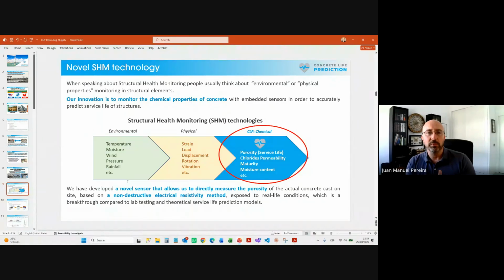What we correlate to with this non-destructive electrical resistivity method is the porosity of the concrete, okay? Porosity has an impact on everything because it shows you how the concrete is evolving. So it relates to strength, chloride permeability, carbonation, and also the maturity of concrete. It can also be related to damages that happen later, for instance alkali silica reactivity, which starts with micro cracking the concrete from the inside, and delayed ettringite formation, DEF. Any of these expansive damages increase the porosity because they form micro cracks. So we can detect both how the concrete improves over time and if these things happen, okay? And like I said, it's a non-destructive test, so we can measure this continuously. That's why it's a monitoring system, okay?